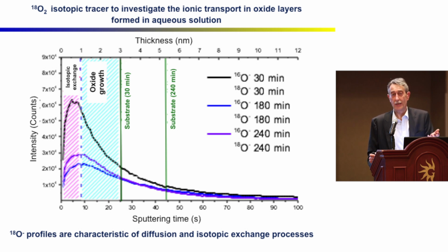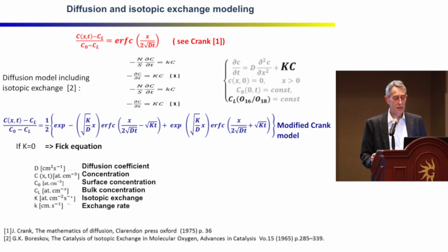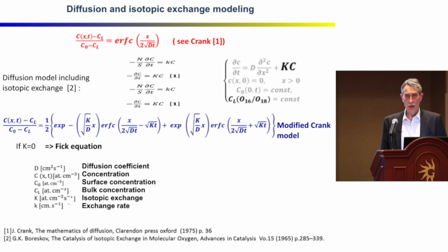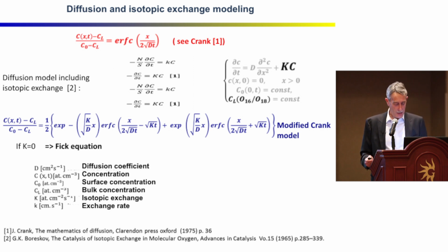So no technique is perfect, like human beings. So we have to now take into account that at the same time we have diffusion and isotopic exchange. So we have to do some mathematics to fit and interpret the data. On one hand, we have the solid state diffusion. This is just expressing Fick's law, and I think a good book for that is The Mathematics of Diffusion by Crank. But then we also need to take into account the isotopic exchange between oxygen 16 and 18. And so we come out with this equation here, which we call the modified Crank model, which is a modified Fick equation, taking into account the isotopic exchange.